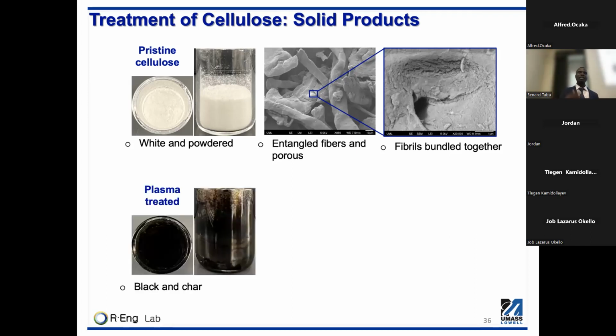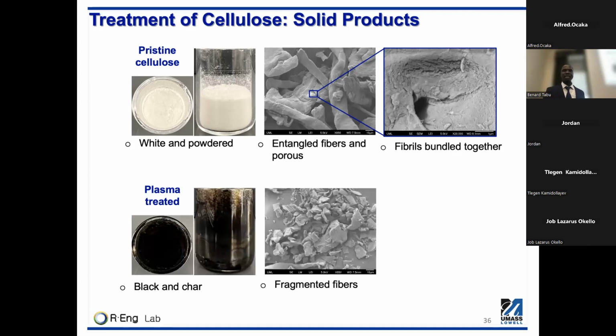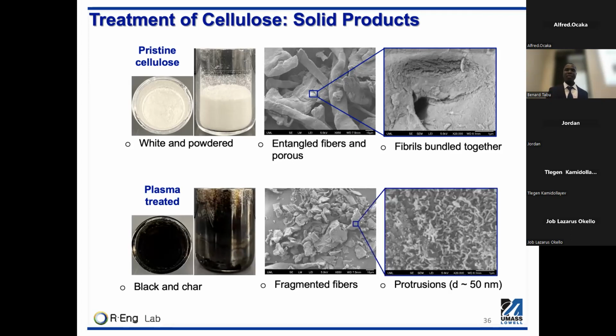For the plasma-treated cellulose, it's really dark, probably due to charring. Under the microscope at low resolution, we see that it consists of fragmented fibers. Under high magnification, we see that these fibers consist of protrusions. The fibrils are loosely attached together, and you can easily see them. They are very visible, and when we measure the diameter of those fibrils, they are about 50 nanometers.